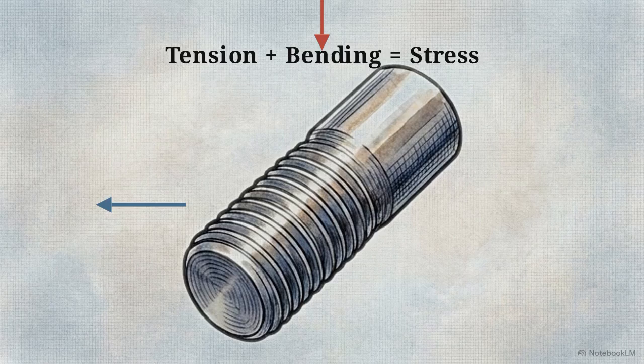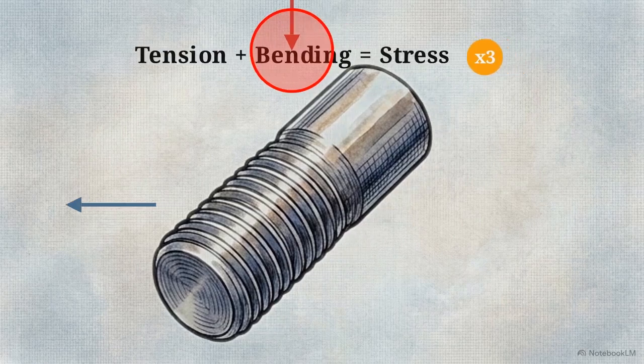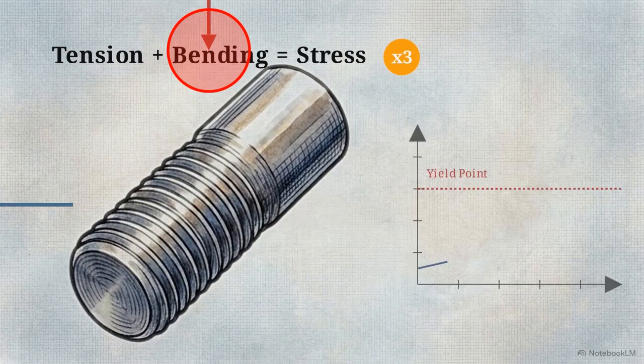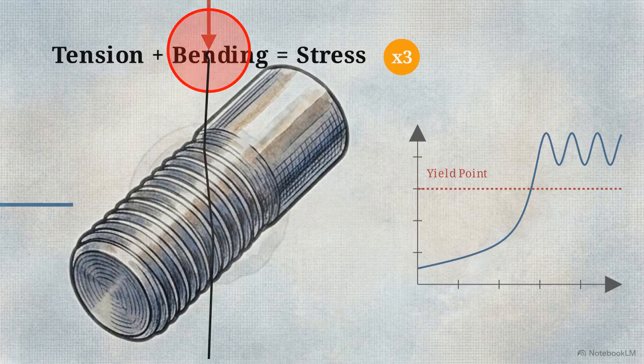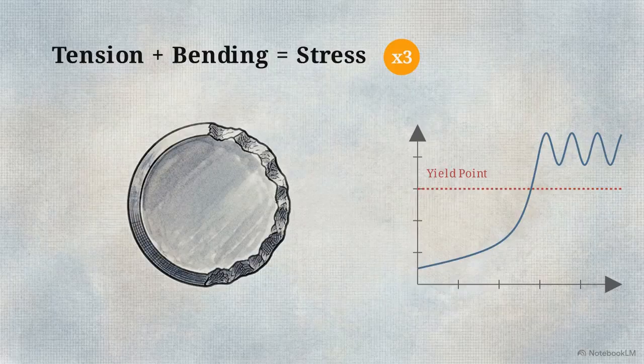The mathematics of this interaction are lethal. The geometric multiplier of the thread runout, compounded by the extreme bending eccentricity from the crowbar effect, spiked local stresses far past the grade 5 steel's yield point. Once localized yielding compromised the thread roots, the normal cyclic pressure variations of the fluid line took over. The microcracks formed, competed, and rapidly propagated through the shanks via fatigue.